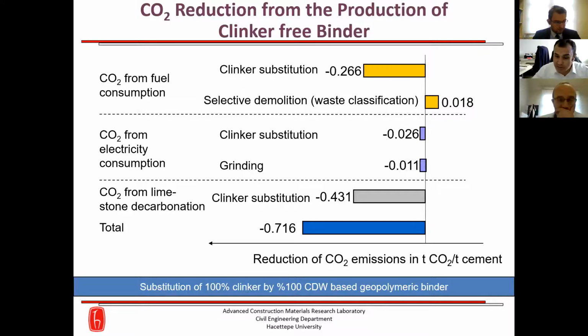As a result of the clinker substitution with 100% CDW-based binder, a reduction in the specific fuel-derived CO2 emission is approximately 266 kilograms per ton of the cement. Additionally, energy is necessary for the selective demolition of the construction demolition waste. This is around 18 kilograms of carbon dioxide per ton of the cement.